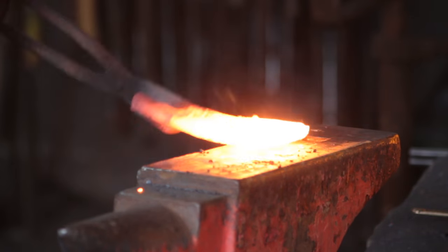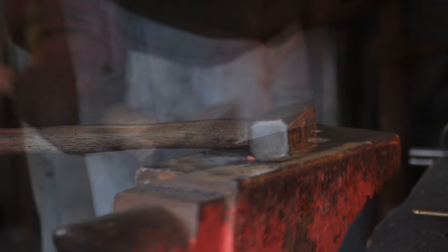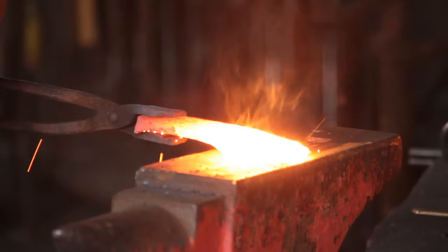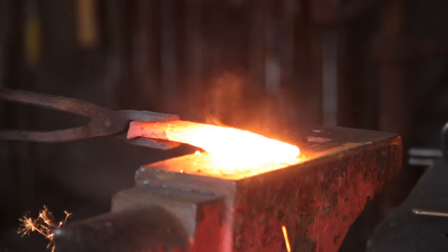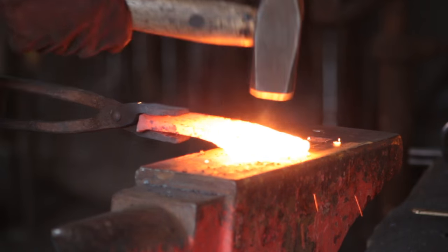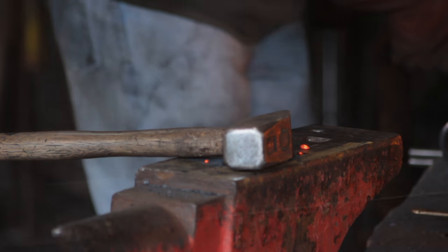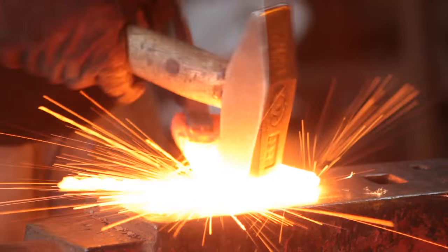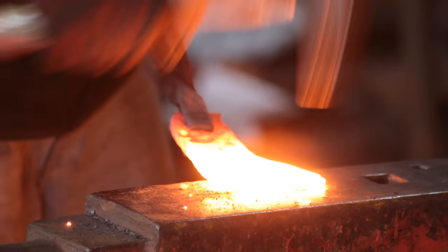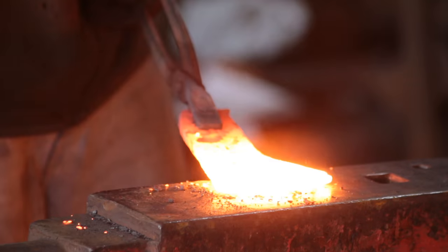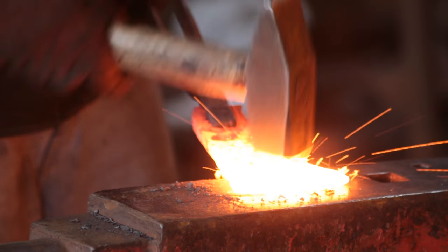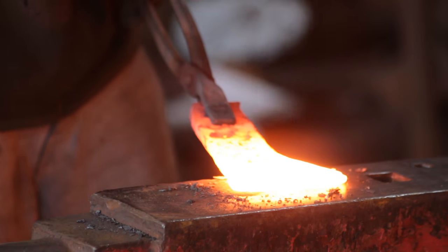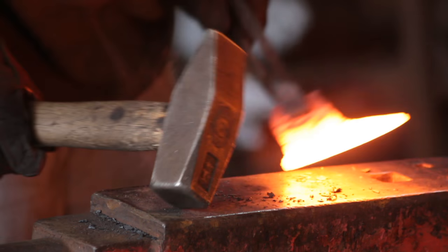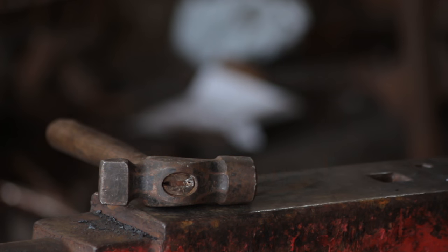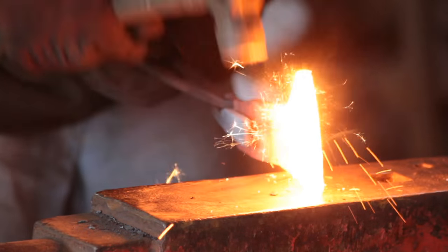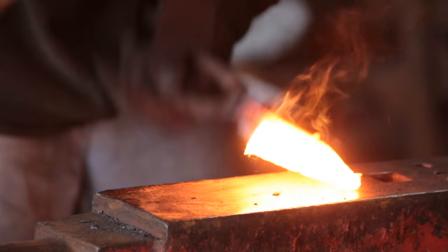So like I said before, wrought iron tends to be self-fluxing anyway because of the silica content. I didn't use anywhere near as much flux as I normally do for welding in steel bits. It's altogether very nice. The one thing I should have been careful of is how soft the wrought iron is. I should really have used a smaller hammer for it to save spreading the material quite so much. When you work mostly in mild steel, you do tend to forget that.